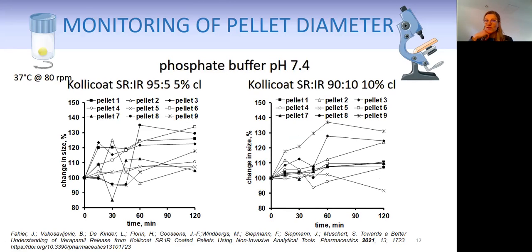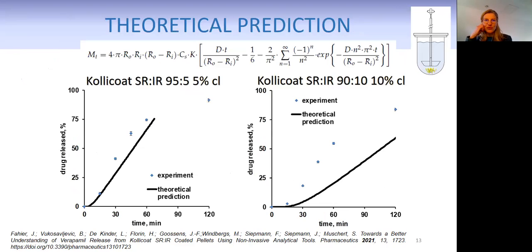When we expose the pellets, however, to phosphate buffer 7.4, the pellets swell to a much greater extent. You can see, for example, pellet number 6 here is swelling, swelling, swelling until it reaches like 135% of its initial size, 35% more of the initial size. Other pellets do swell and then suddenly decrease in size. So here we could actually have an onset of rupture. Even more pronounced with the thicker film coatings of the 90-10 blends, where we have pellets that swell and then suddenly decrease in size or slowly decrease in size. So we could actually have, instead of diffusion controlled drug release, a rupture of the film coating, the crack formation.